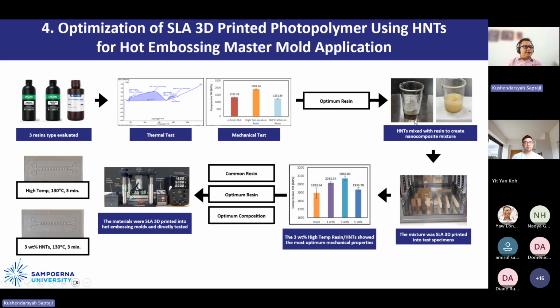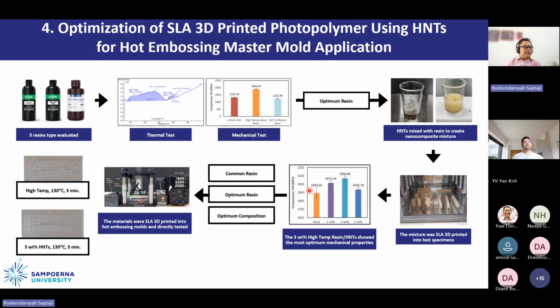Then we prepare the HNT, which is halloysite nanotube, and we do the mixture. After that, we perform the test again with additional 1, 3, and 5% of HNT in the high temperature resin, and we compare the results. There's an improvement of the mechanical properties compared with the standard resin. After that, we created the mold for hot embossing and performed the hot embossing test using this machine, and we got some good results. For the 0% addition of HNT, the mold was broken after a few embossing cycles, but for the 3%, it produced a good